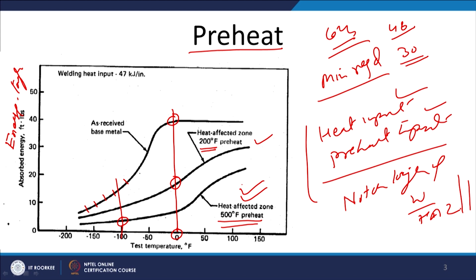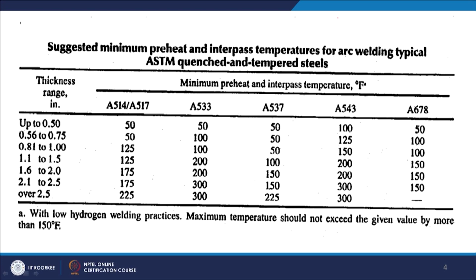Now we will see. Keeping things in mind, especially the thickness of the plate, which will be determining the rate at which heat is being extracted from the weld as well as heat affected zone. So the thickness and the kind of composition, different steels having different alloying concentrations, that in turn will be affecting the carbon equivalent. So the conditions under which a particular kind of phase transformation takes place will also be changing, and therefore we find that the minimum preheat or interpass temperatures vary significantly with the change of the thickness of the plate which is to be welded.